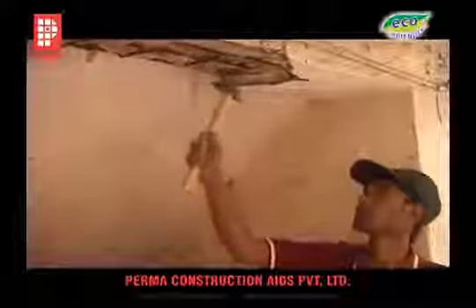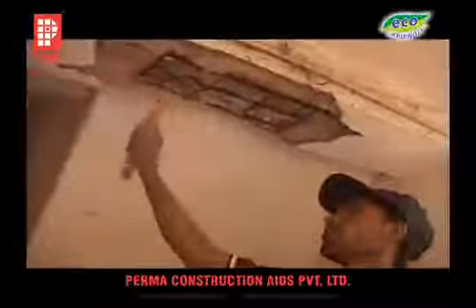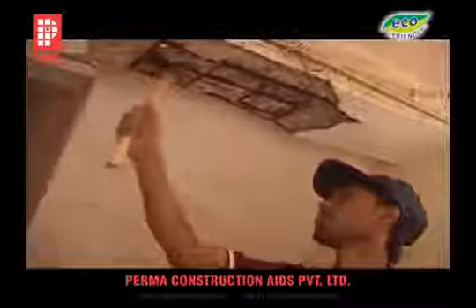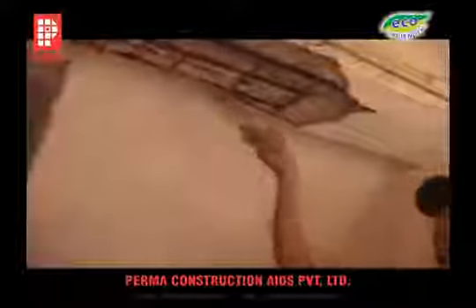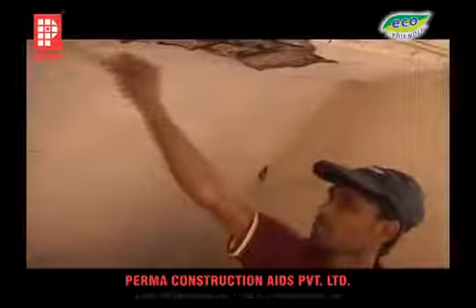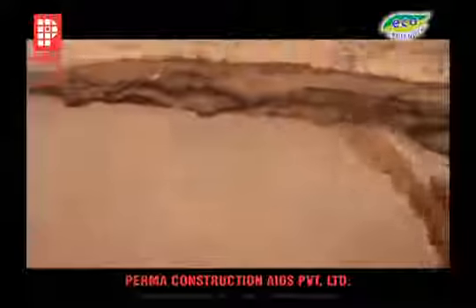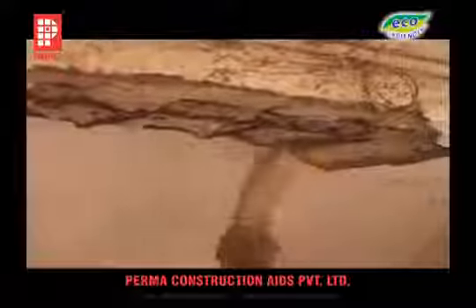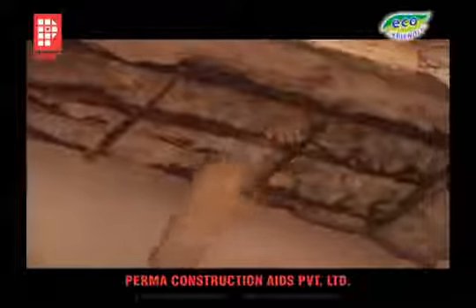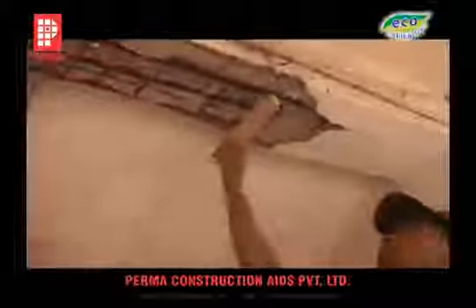This rehabilitation process involves careful removal of cover concrete from the reinforcements to the extent it is corroded, and cleaning them with a wire brush. Additional reinforcements are added and welded to the existing reinforcement to make good the loss of steel, which is lost in corrosion.